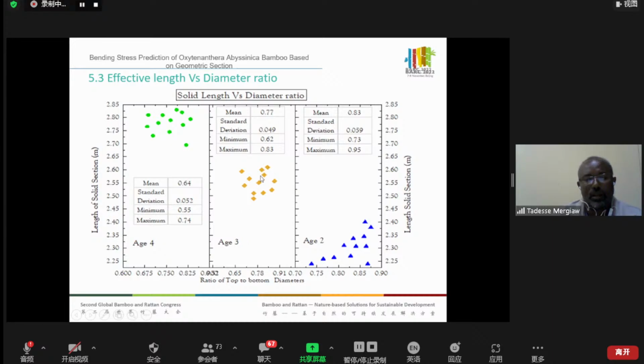For Age 3, the ratio of the top to bottom diameter is an average 0.77, while the length is less here, 2.6, 2.5 resulted. The other one at age 2, here it's a 0.83 mean diameter ratio, top to bottom, but the length of the solid section is below 2.4. So from this result, we can see that a maximum of up to 2.8, 2.85 meter solid section length is available at age 4 when the diameter ratio is 0.64.